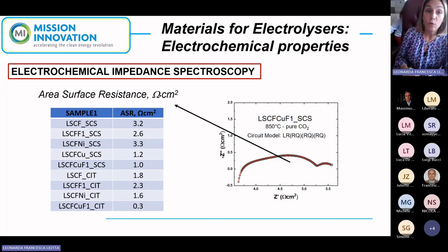By modeling this data, we can obtain information about the area surface resistance due to the ionic electronic transport of the material, but also the reaction transport, the heterogeneous reaction above the materials. These properties are influenced by the composition, as we can see here.